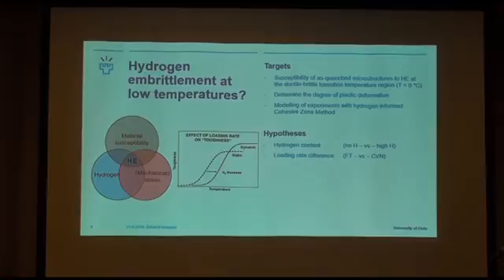So our target was to test the susceptibility of these microstructures to hydrogen embrittlement in the ductile-to-brittle transition temperature region, to determine the degree of plastic deformation, and to model and verify the cohesive zone method in these circumstances. And our simple hypotheses are that hydrogen content plays a role even in these circumstances, and that there's a loading rate difference between impact toughness tests and relatively much slower fracture toughness tests.